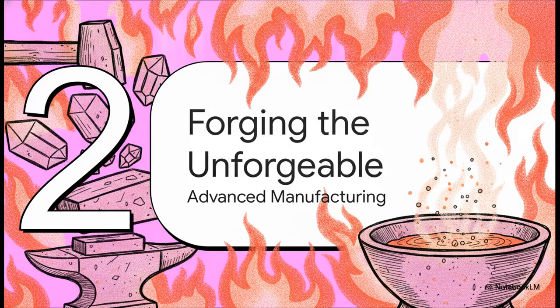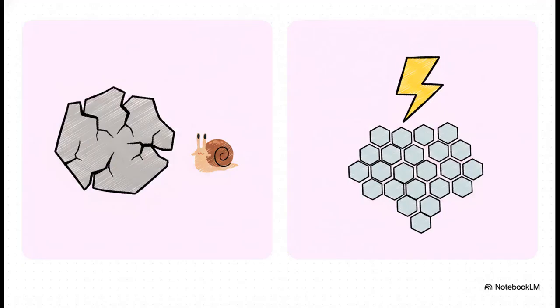Section 2, forging the unforgeable. For decades, ZrC was actually held back because conventional hot pressing was just way too slow. It caused the individual crystalline grains inside the material to grow too large, which basically left you with a brittle part. But the real game changer is Spark Plasma Sintering, or SPS.